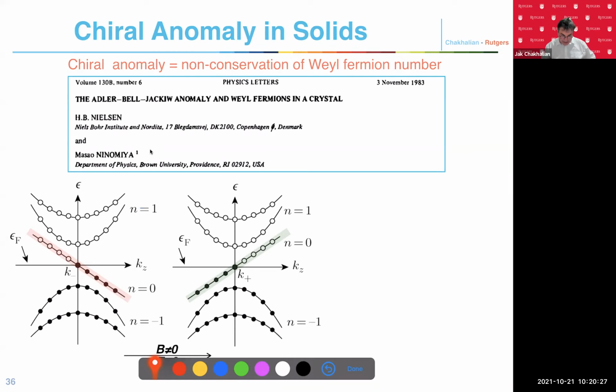And then in your material, if you have Weyl fermions, you have very special Landau levels. In a high magnetic field, this is the Weyl node, and this is another Weyl node, one with chirality +1, another with chirality -1. So here you have two Weyl nodes sitting next to each other. Or you can think about this as the North Pole, this as the South Pole. And in the high magnetic field, these monopoles will go into linearly dispersing states, like in Dirac particles. It's a linearly dispersing state, like in a relativistic Dirac particle, and that's the only state which is fully occupied here, and fully unoccupied there. Everything else is empty or fully occupied. So if scattering or some kind of current occurs, it should move electrons between those two.